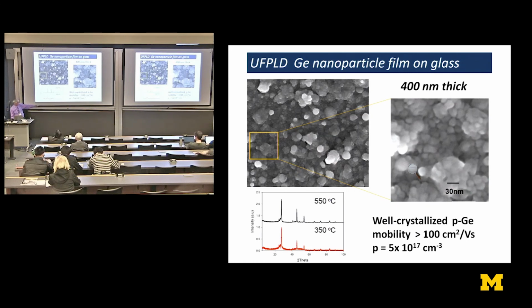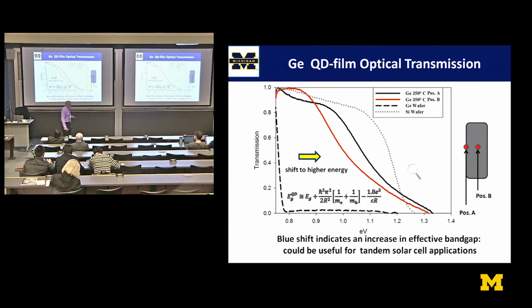And free charge density is on the order of 10 to the 17. So what's interesting about this is that one can actually get a semiconductor material in nanoparticle form that has an effective band gap that is quite a lot larger than what you have in the bulk. This is the bulk, the dashed line, and it's blue shifted over by a substantial fraction of an eV, almost to the point where silicon has its band gap. So in other words, you created a material which has properties that are somewhat intermediate between germanium and silicon by making it into a nanostructure.